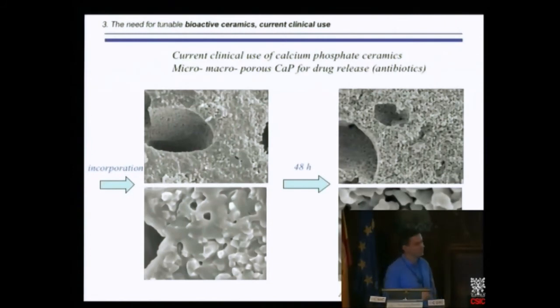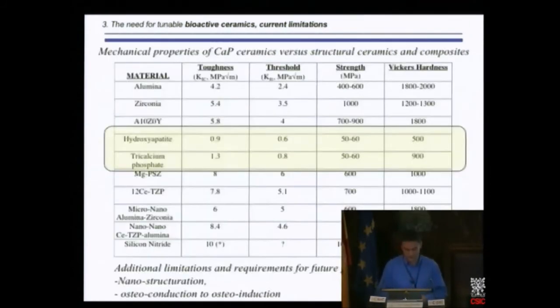And we have tested that also on animals, and now it's on the market. So how to play with that? You have to play with the porosity features, pore content, pore size, for the speed of diffusion. One problem with calcium phosphate today is their mechanical strength. Again, mechanical strength. I am a monomaniac. What you see is the toughness. Hydroxyapatite and tricalcium phosphate have a toughness of only 1. This is about the same as glass. So these are really brittle materials.